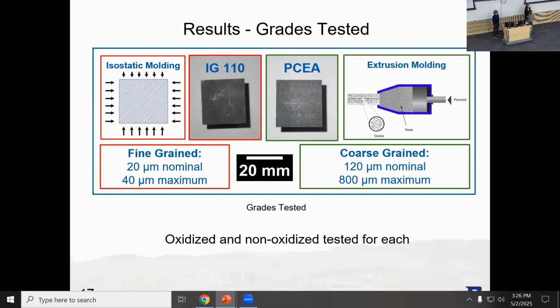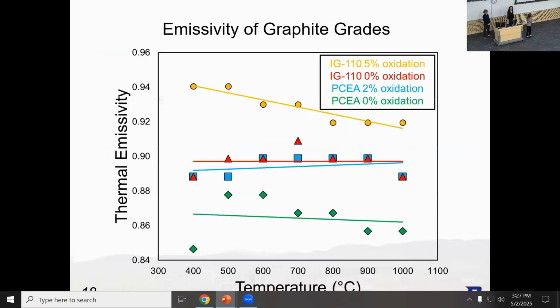Earlier, I told you we were interested in 6 grades of nuclear graphite, but we narrowed the scope of our presentation to focus on the fine grain IG-110 that was formed via isostatic molding and the coarse grain PCEA formed by extrusion. In addition, we were delivered an IG-110 sample that was oxidized to 5% mass loss and a PCEA sample oxidized to 2% mass loss. We didn't have 5% because the PCEA took a lot slower to oxidize at 500 C, and that's what we got from our sponsor. This is a summary of our experimental results, where we show thermal emissivity versus temperature.